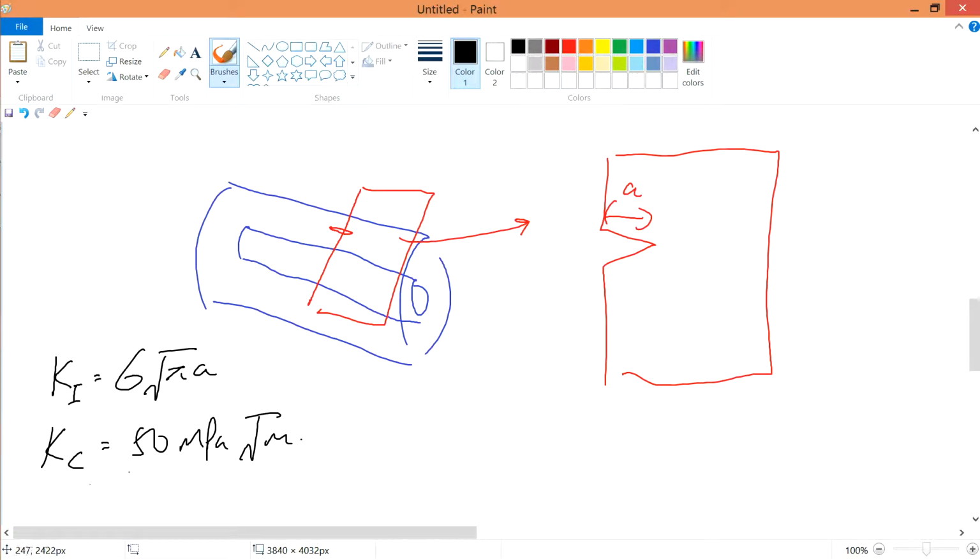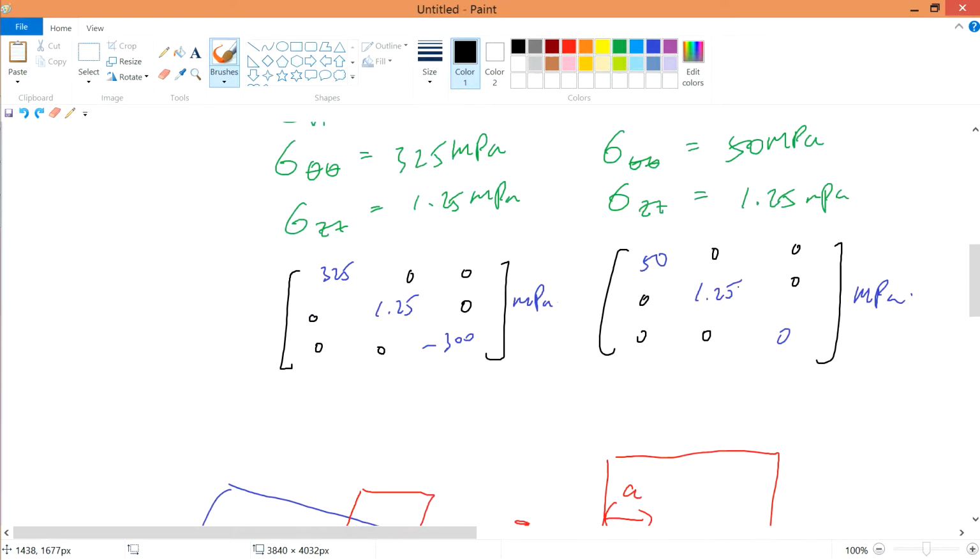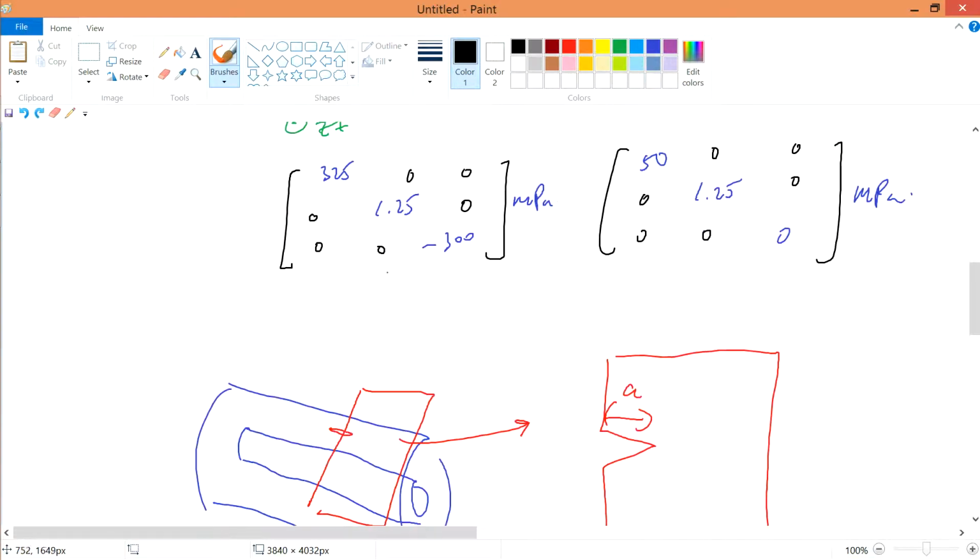I actually give you the steel fracture toughness over here, 50 MPa square root meter, and they ask you to find this crack length. In order to find it, you find the worst case scenario that will create a crack. The worst case scenario is the largest stress acting upon your vessel. So it's your 325, because comparatively, of all these values, the 325 is the scariest one.